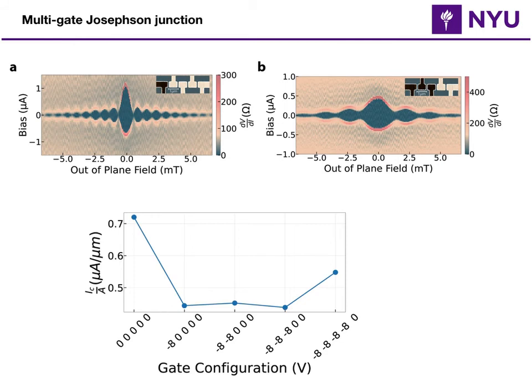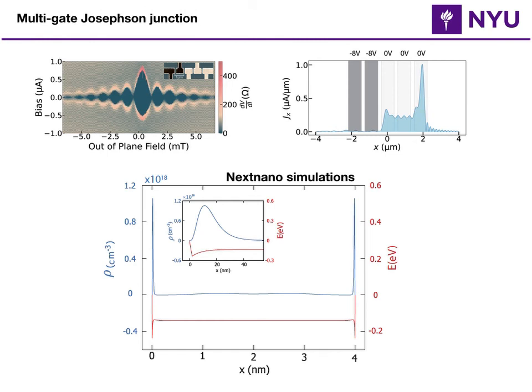So this very junction could be used for realization of these topological states. And one thing that would be really cool to do is to change the widths of this kind of effective wire, right? On the top left, I show current that can go through 5 mini gates. The black means the current is blockaded. The right side shows 3 blockaded and 2 allowing the current to pass. And we can do that for all sorts of configurations and look at the way that the width changes. And we can indeed see a monotonic decrease of the width of the junction, which is very promising once we have stabilized topological states here.